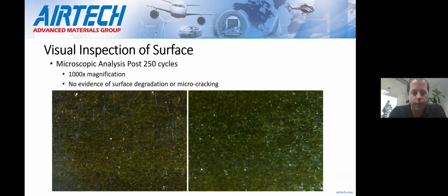And also looking at things under the microscope, about 1,000 times magnification here. Really no evidence of microcracking in that surface. The Achilles heel of traditional thermoset composites is that they will microcrack. And over time, those microcracks will ultimately lead to a loss in vacuum integrity or gross delaminations. Really not seeing any evidence of that whatsoever on the tool surface.